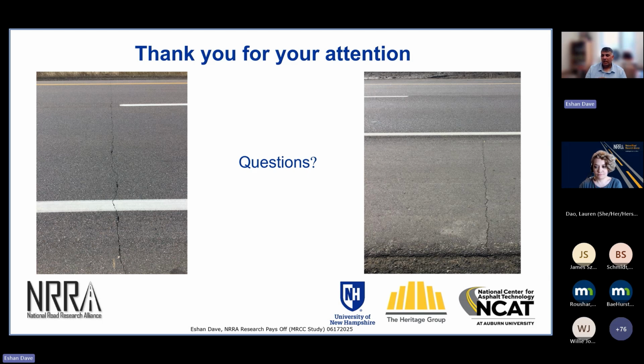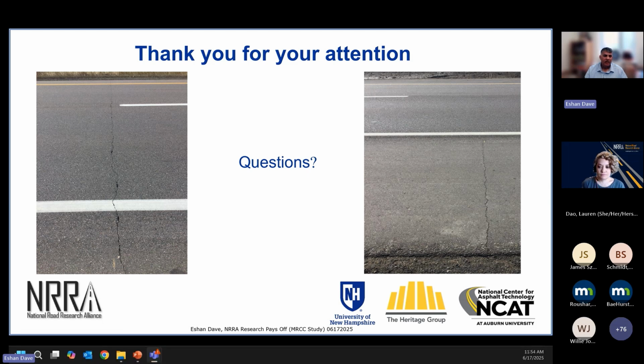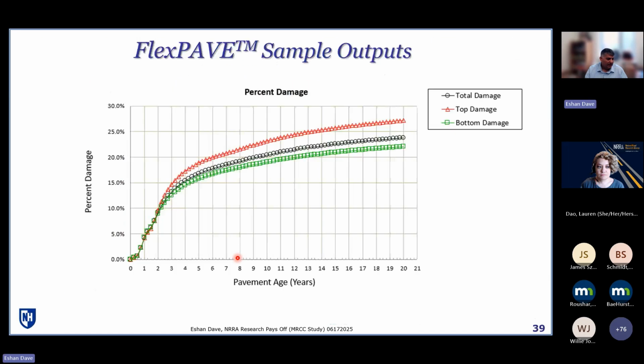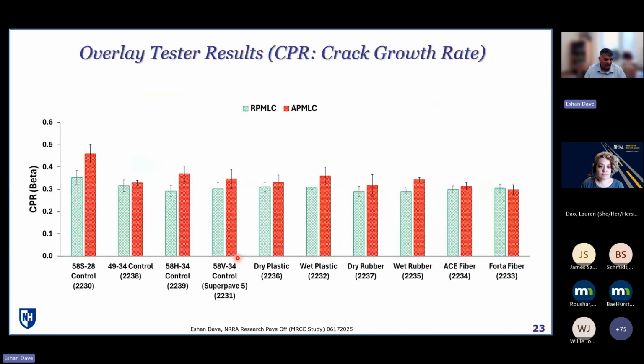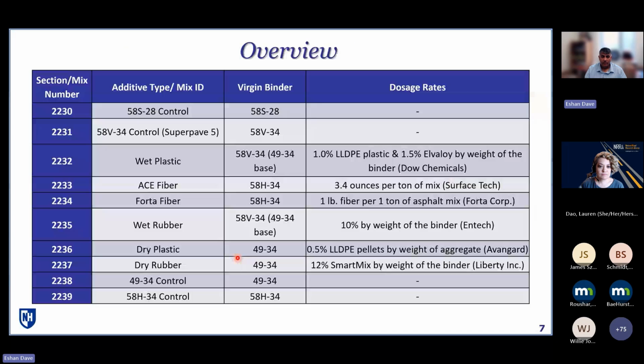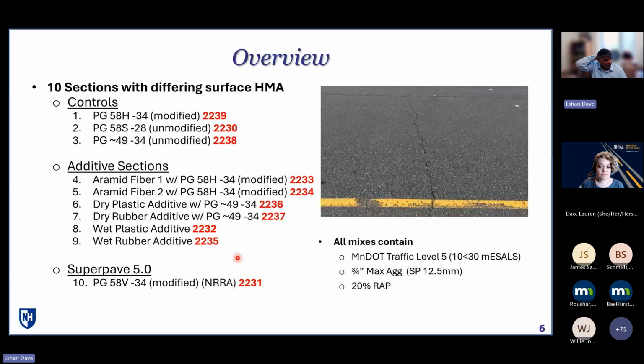Keep in mind once again that this being a companion effort with additive group experiment, essentially the way the mixes were optimized initially was by doing balanced mix design, testing using Hamburg and CT index in order to get them to a certain minimum CT index and passing Hamburg numbers. And so there were some modifications done on the basis of that. But also that's why you see those dry additives have such a softer initial binder grade in order to activate them. But as far as my memory serves, there was not really additional binder needed or added, at least not in an appreciable way for those dry additives.